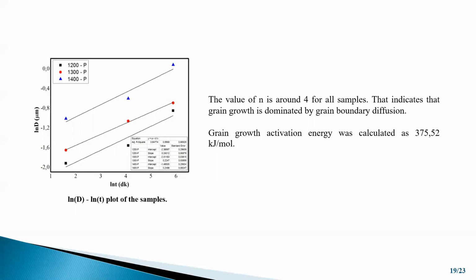Using this n value, we also calculated the grain growth activation energy, for the first time to our knowledge, for our products, which is equal to 375.52 kilojoules per mole for a 6-hour sintering process.